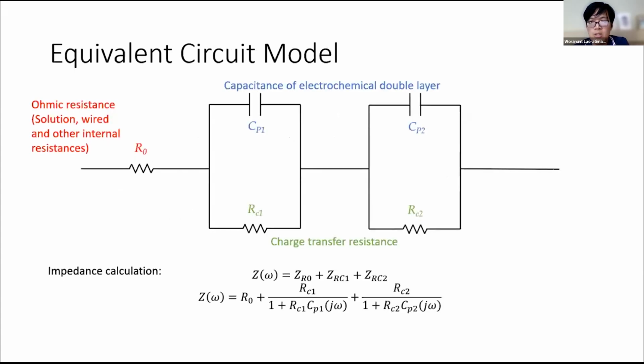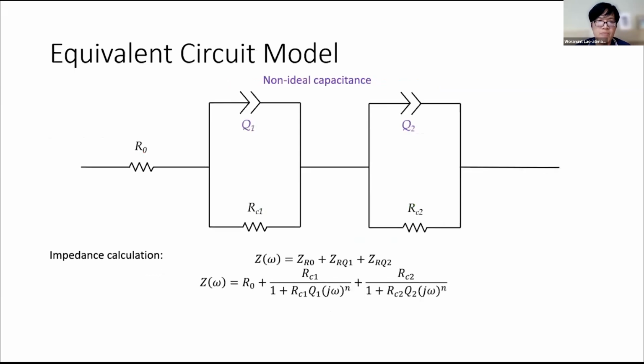This slide shows the equivalent circuit model with the impedance equation. R0 represents the ohmic resistance. CP is the capacitance of the electrochemical double layer, and RC is the charge transfer resistance, and the equation is shown below. As I mentioned before, we replace the capacitor with the constant phase element, or Q, and the equation changes to this equation. This model with the constant phase element was used to fit the data from the EIS results.